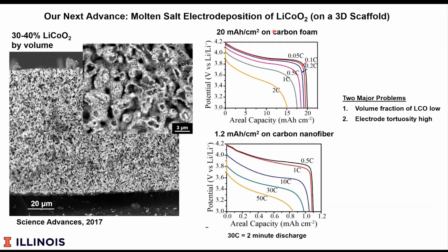But what we're able to do here is electrochemically grow very high quality lithium cobalt oxide. And so lithium cobalt oxide is sort of the prototypical material. It's one of the first materials used in lithium ion batteries. It's still used extensively. An issue is that cobalt is rather expensive, and so in many commercial systems, some of the cobalt has been replaced with other species like nickel or manganese or aluminum, but fundamentally lithium cobalt oxide still remains sort of the centerpiece of many systems.